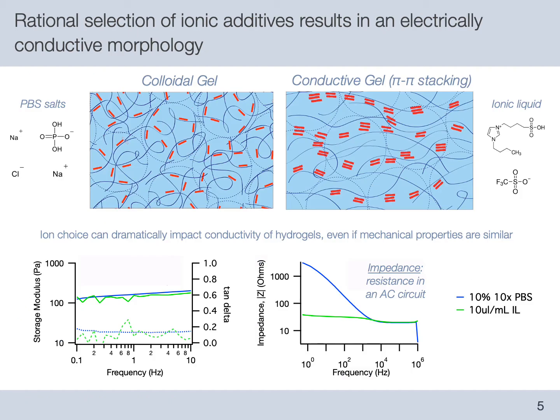Interestingly, we found that certain ionic species that are known to enhance conductivity in PEDOT:PSS films similarly seem to enhance conductivity in these hydrogels. For example, our group previously found that the ionic liquid shown in the top right boosted PEDOT:PSS thin film conductivity by disrupting the interaction between PEDOT and PSS, thereby allowing PEDOT units to form conductive pi-pi stacking junctions amongst themselves.